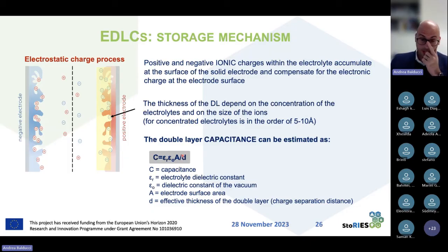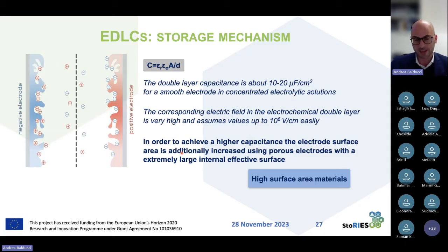That means how thick the double layer that we are forming between the electrode and the electrolyte will be. Now, if we look at this equation, it's clear that the best way to increase the capacitance, and again, this is very important to increase the energy that we are storing, is to have a very thin double layer. But what is also very important is to realize a system in which the area where this double layer is formed is very large. What does this mean? It means that if we are using, for example, a flat surface, that probably is not a good choice because we are not able to maximize the area. What we try to do in this system is to utilize electrodes which have extremely high surface area, because this high surface area gives us the possibility to maximize the capacitance of the electrode and consequently to increase the energy of the supercapacitors.